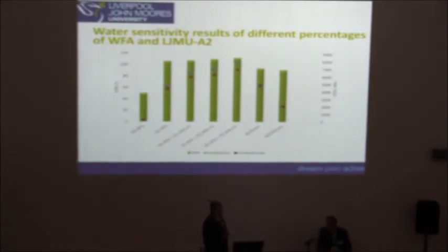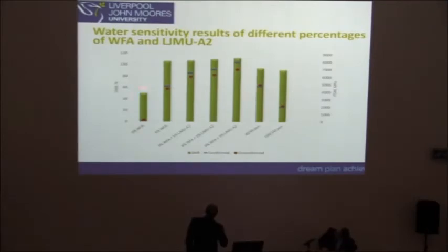In terms of water sensitivity, this is the control cold mix, and these are the two hot mix controls. This is the hard and this is the soft, and this is cold mix with waste fly ash. This is with additives: 1% of LJMU-A2, 2% and 3%. We can see that the wet stiffness, which is the blue one, is more than the dry stiffness. So our new mixture is more durable than the three control mixtures, the two hot mix